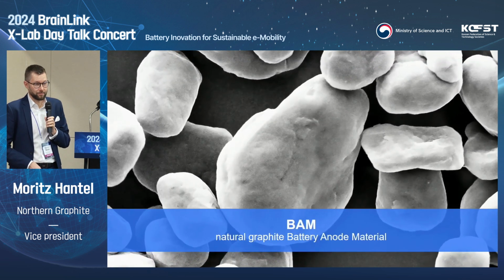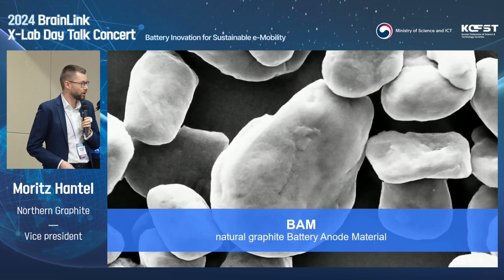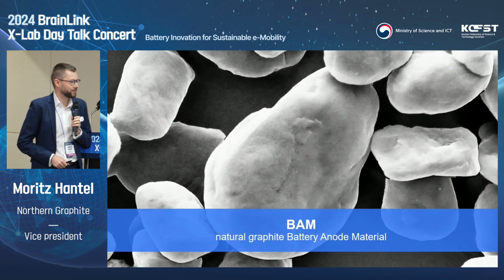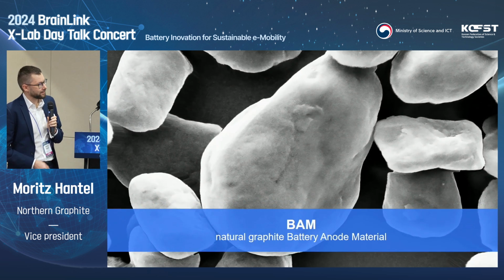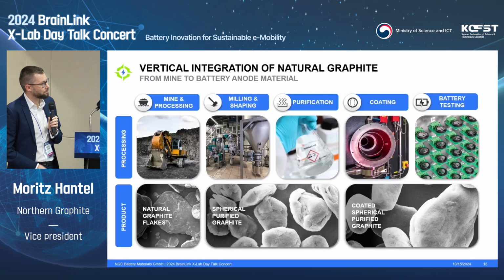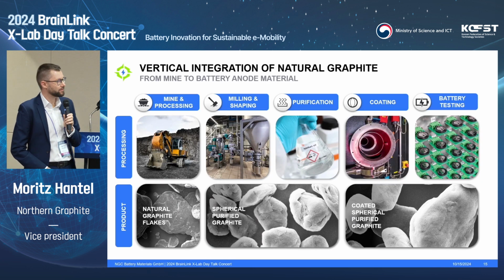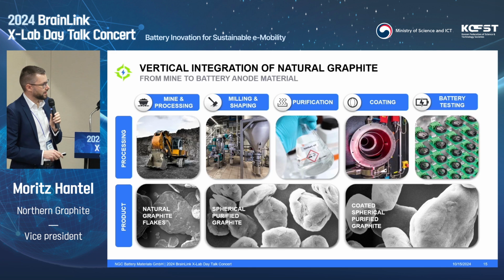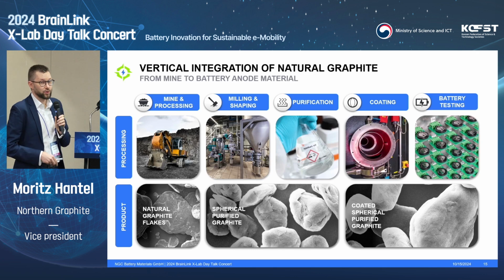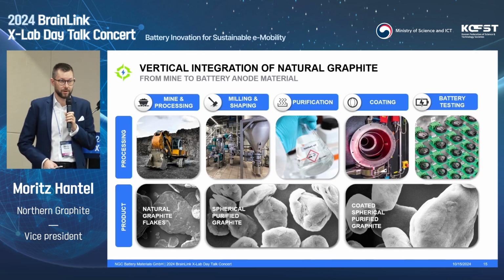So what do we do actually? The first thing we're doing is BAM, what we call battery anode material, to be a little bit diverse from the anode active material. In the end, it's a natural graphite-based system, meaning we're working on the full integration, starting on the left with the mining, going to milling and shaping, purification, coating, and testing before it goes to the customers. From a product perspective, this means we have the flakes, which also go in other industrial markets. We have an intermediate product, spherical purified graphite, SPG, and we have the final coated spherical purified graphite, which is the active material used in the battery.